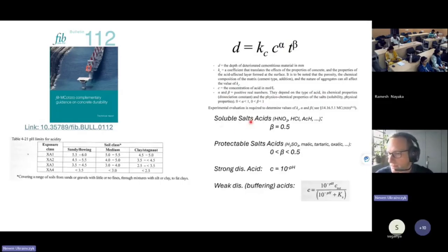So if you have a soluble salt acid like nitric, then this beta is 0.5. But if you have a protective salt acid like sulfuric acid, because it makes a protective layer, it also closes the porosity because of the precipitation of gypsum, but it also makes cracks. So then you can change this beta factor. And you can have a strongly dissociating acid, which basically means that you have a very high equilibrium constant. Then you can easily calculate the pH.